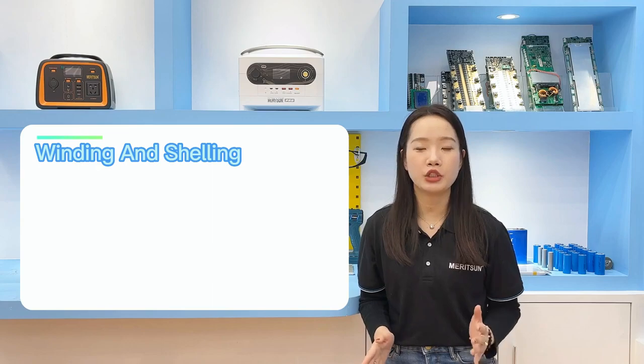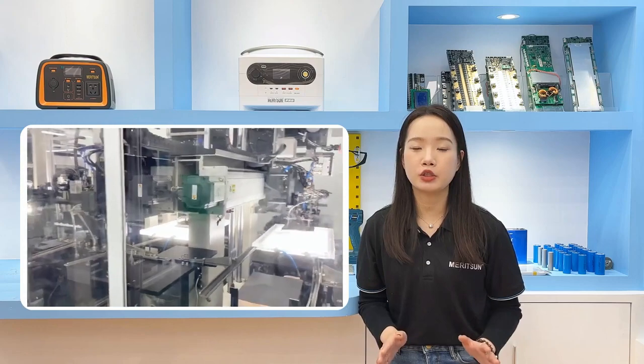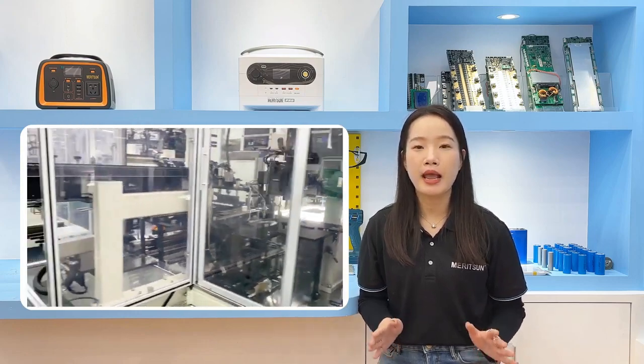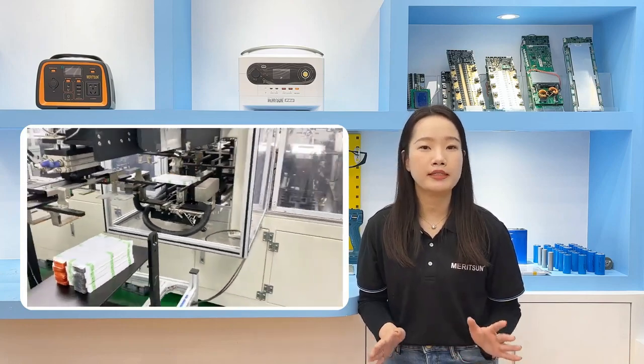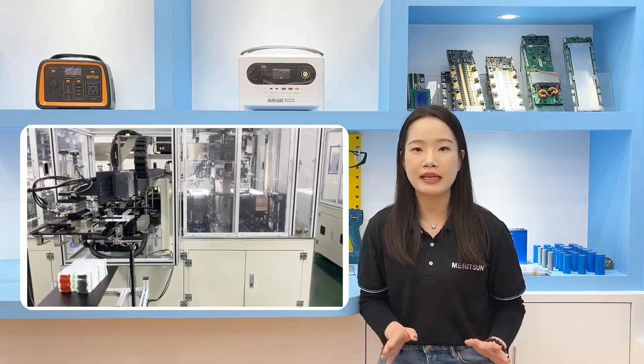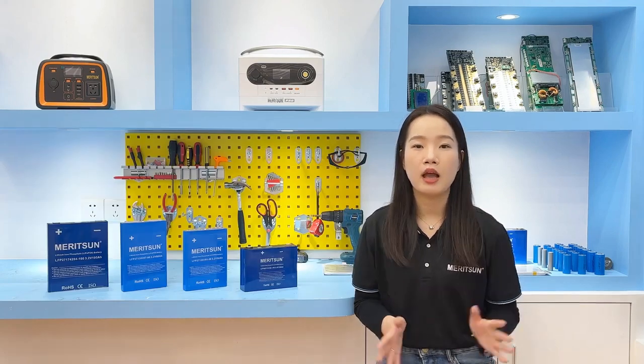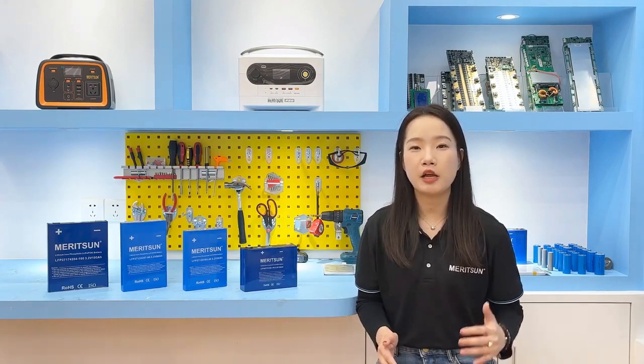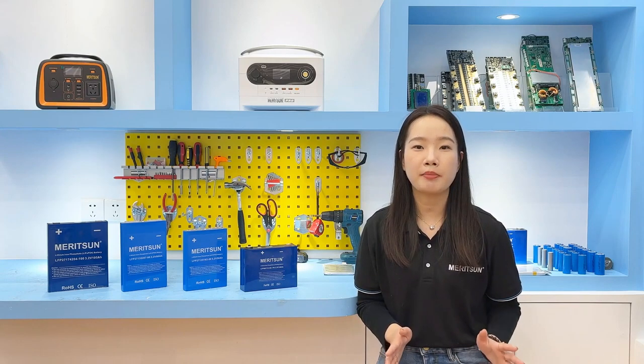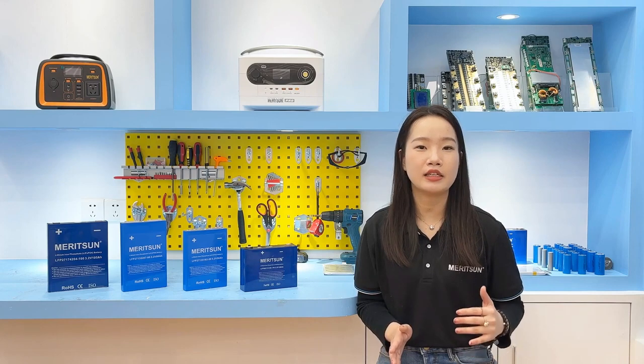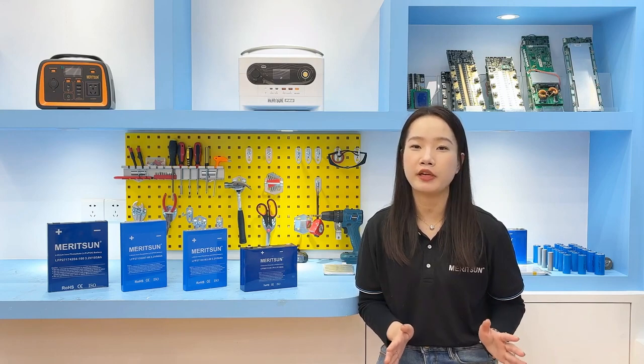The fourth process is winding and shelling. Place in order the positive electrode sheet, separator, negative electrode sheet, and separator from top to bottom, and make the battery cells by winding. Depending on the type of cell, two basic cell assembly methods are generally used: stacking and winding, and the entire process is usually carried out on fully automatic equipment. After winding, the assembled cell structure is connected to the terminal or the cell's tabs by laser welding machine, and the subassembly is then inserted into the cell's metal housing for sealing, leaving an opening hole for the injection of the electrolyte.